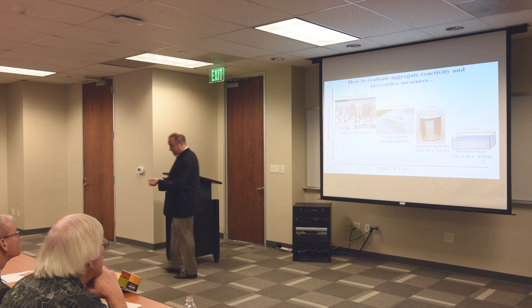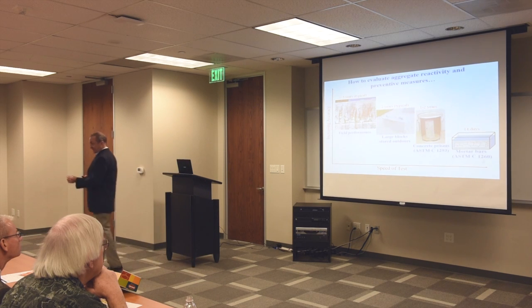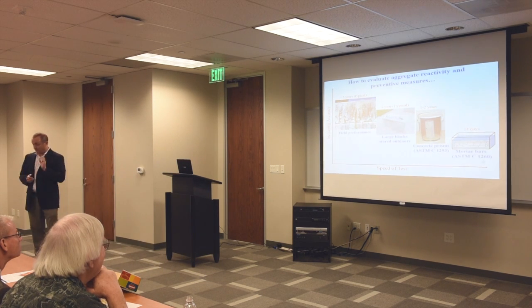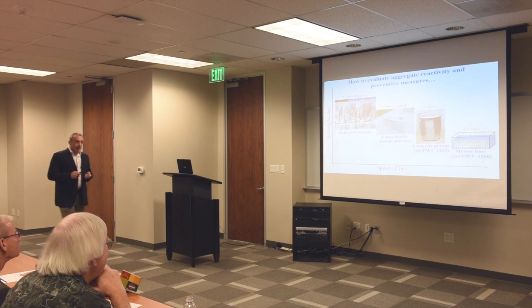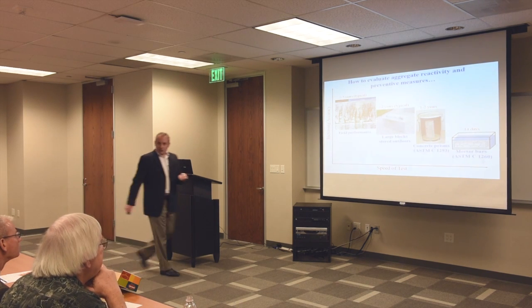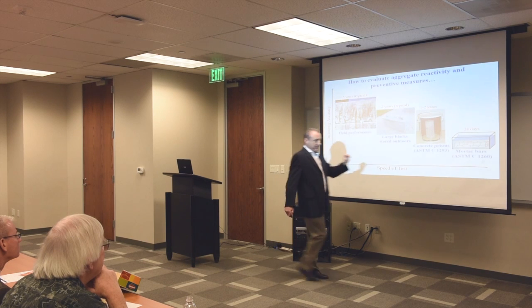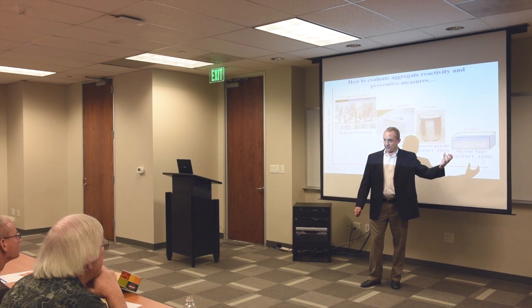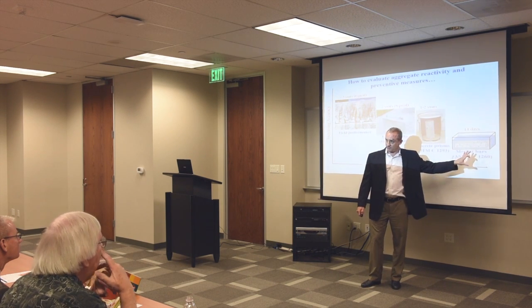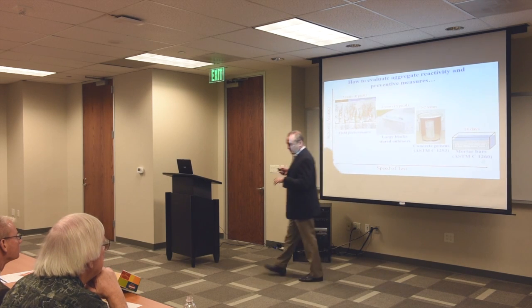If we had a scratch and sniff test, it would be adopted instantly by every highway department. In fact, we're working on that as we speak. But what they want to run, they want results in 2 weeks. And the way to do that is to take a mortar bar comprised of that aggregate and put it in Drano solution at 176 Fahrenheit.